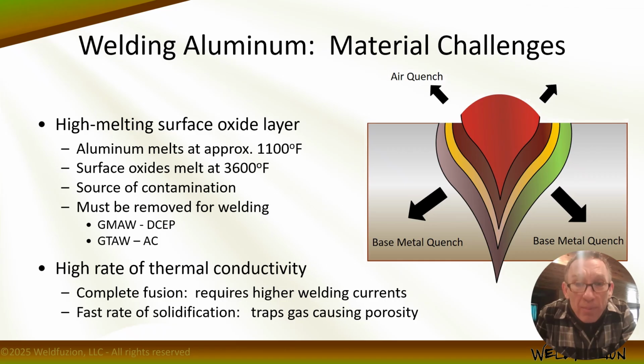Oxides can be removed chemically with surface cleaners, mechanically with dedicated aluminum consumables, right? Flap discs, grinding discs, and things like that that are specifically designed for aluminum, and by using stainless steel wire brushes and wheels that won't cross-contaminate.